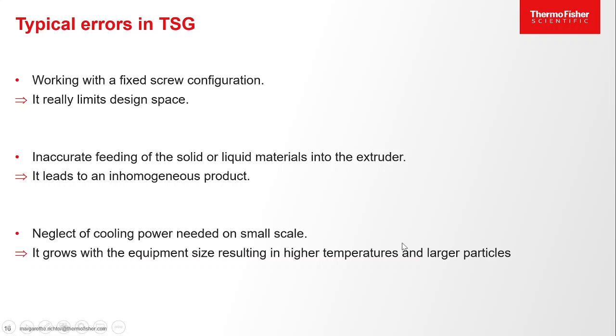So typical errors that happen in twin-screw granulation, I think it does make sense to have a closer look into that topic as well. What I see quite often, especially in publications, is that the researchers work with fixed screw configurations. So they have the setup the way it is. They hesitate to change anything in the configuration, which is maybe a good start point, but it really limits the design space. So keeping this fixed will limit you a lot, and it makes sense to change the screw configuration and adapt it to what you need, to your formulation.